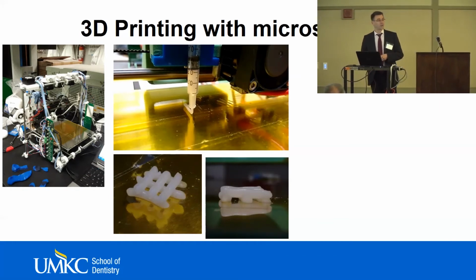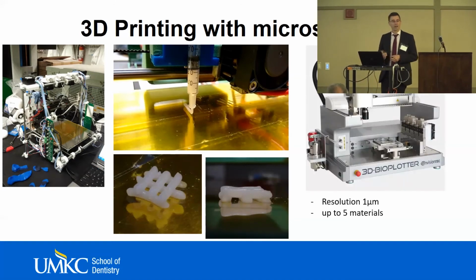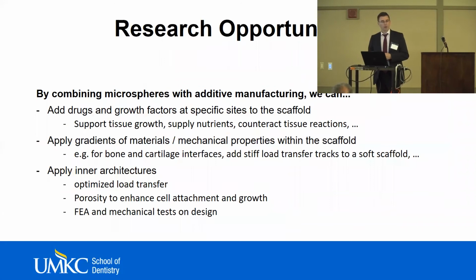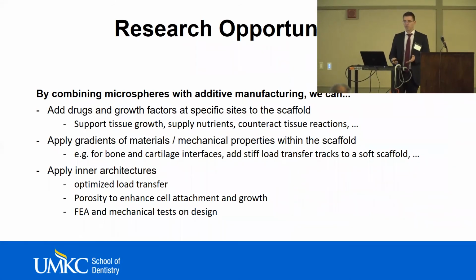Fortunately, the School of Dentistry at UMKC has recently invested in a high-end bioplotter. So with this one, I have higher pressures for printing. I have a printing resolution of up to 1 micron, so I can really focus on certain areas within a scaffold, and I can use up to 5 materials for the same scaffold. So I can really play around with different materials at the core of the scaffold and at the outer side. By combining 3D printing and additive manufacturing with the microspheres, we can add drugs and growth factors at specific sites in the scaffold, and that will allow us to release those different types at predetermined times after implantation to support tissue growth, to supply nutrients, to counteract tissue reactions, and so on.